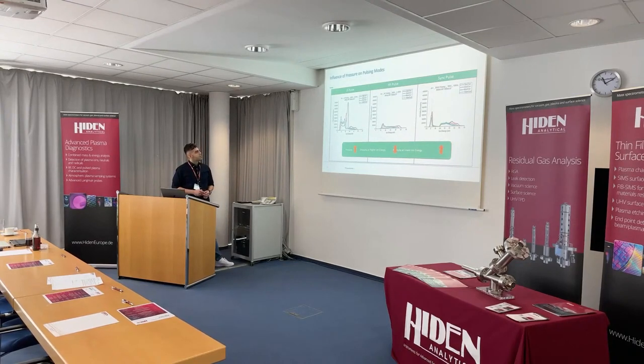In the case of LF pulse, HF pulse, and sync pulse, for all of them, when we increase the pressure, the intensity at the higher ion energy range decreases, and the intensity in the lower energy range increases for all of the pulsing modes. This is the same.